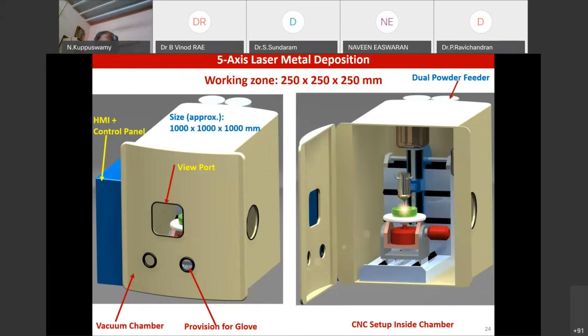Even if you are depositing in argon, you have to remove the residual oxygen. To remove the residual oxygen, you have to start evacuating it when you start the process. That means you have to get into 1 to 10 power minus at least 2 kind of millibar vacuum, 0.01, which is not difficult to get. The point is, if you don't design this from scratch one, the chamber is leaking everywhere. You will never reach that vacuum.